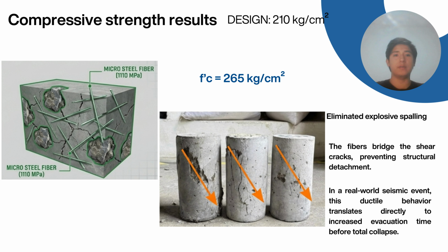The mixture containing both silica fume slurry treatment and steel fiber reinforcement achieved a compressive strength of 265 kilograms per square centimeter, which remained 6% higher than the conventional concrete and 28% higher than the untreated RCA mixture. Although this result was lower than the silica fume only mixture, the steel fibers improved the failure behavior. Instead of experiencing sudden fragmentation, the specimens maintained their integrity after cracking because the fibers bridge the shear cracks, showing a more ductile failure mode. This behavior is particularly beneficial in seismic scenarios because it can provide additional warning time before structural collapse.